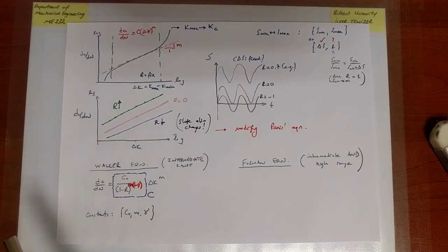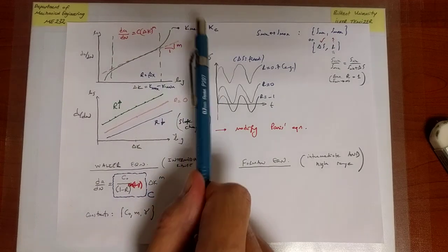Okay, how are we going to do that? Now, the key piece of information that we have is this. I'm going to try to somehow incorporate the fact that eventually what's happening is that we are getting closer to fracture, very close to fracture. Kmax is rapidly approaching the value of Kc, and that's why the line in reality curves up instead of continuing on a line. So let us first write the equation and then interpret it to see how it works.